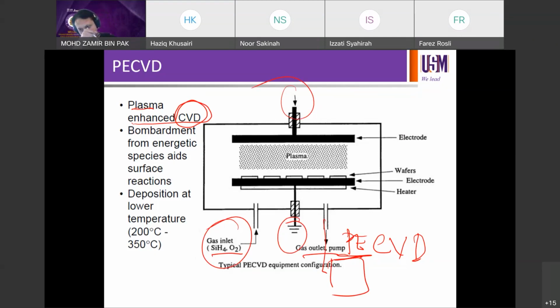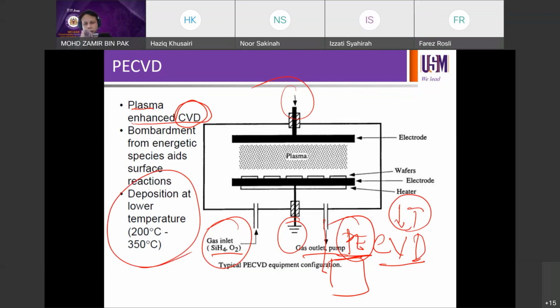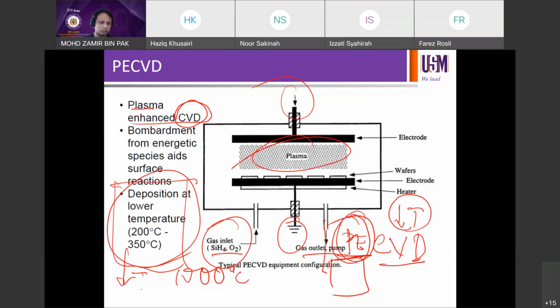It involves bombardment of energetic ions from the plasma, and when you have this plasma enhanced capability, you have an option to reduce the temperature, to low temperature. Because in essence, CVD has to involve thermal decomposition, and to have thermal decomposition you need the heat component, a high temperature component, to decompose. But when you have plasma, that will do the part partially. The plasma will enhance the decomposition, and as a result, the system doesn't need to run at a very high temperature. If you run a typical CVD, you used to run at perhaps 1000 degrees C, right? So with plasma enhanced, since you already have the plasma in the system, which will enhance the decomposition, you then have an option to reduce the deposition temperature.